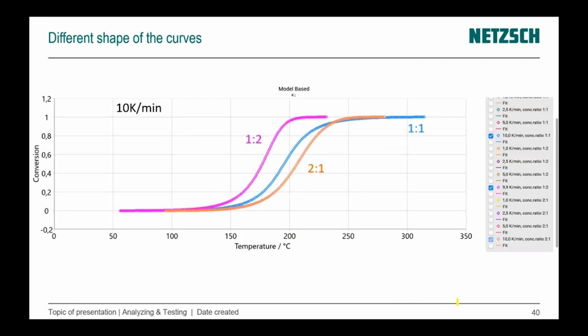The second very interesting part is if we compare the shape of the curve. The shape of the curve, for example for 10K per minute, is totally different. At the beginning, it is more or less the same, but the final part is different. Here, for 1 to 2, the final part is sharper. For 2 to 1, orange is also sharp, but for 1 to 1, this final part is really very, very slow. Why?